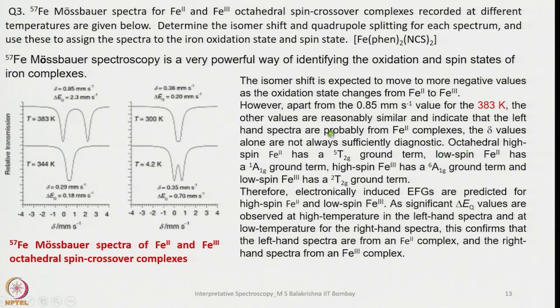Octahedral high spin Fe2 has a 5T2g ground term, low spin Fe2 has a 1A1g ground term, high spin Fe3 has a 6A1g ground term, and low spin Fe3 has a 2T2g ground term. This you can simply look into, how we get it from UV visible spectroscopy. Therefore, electronically induced EFGs are predicted for high spin Fe2 and low spin Fe3, as significant delta EQ values are observed at high temperature in the left hand spectrum and at lower temperature for the right hand spectra. This confirms that the left hand spectra are for Fe2 complexes and the right hand spectra are for the Fe3 complex. This is how you should analyze and conclude about the spectra obtained here.